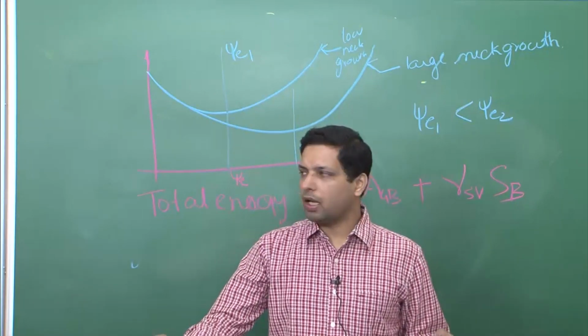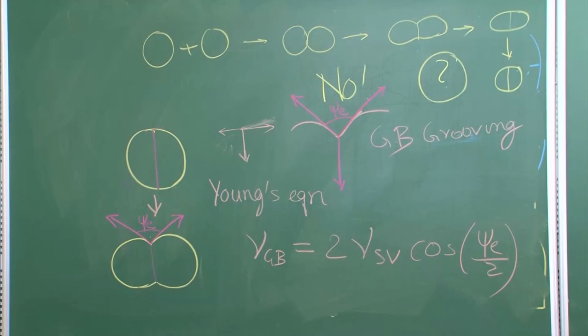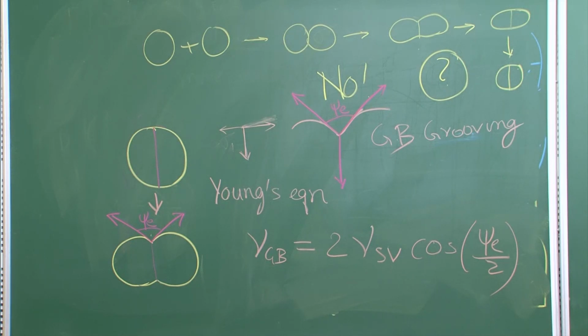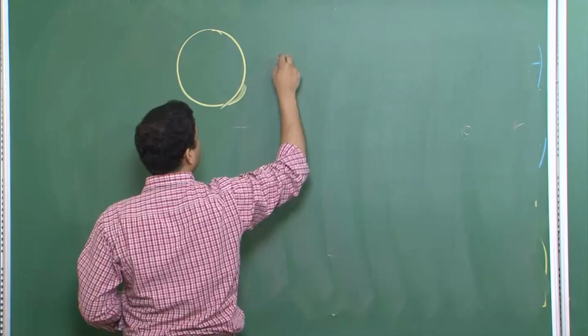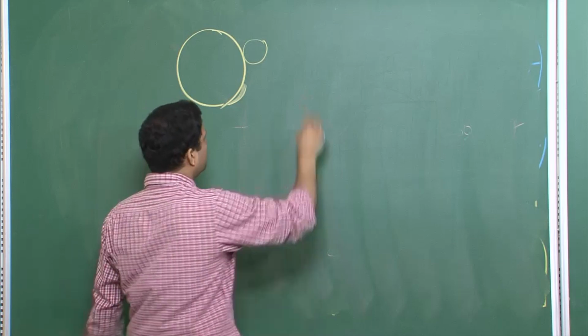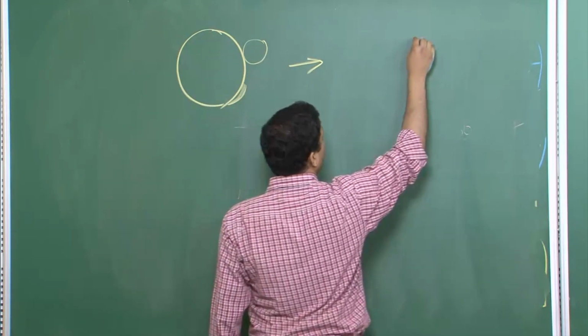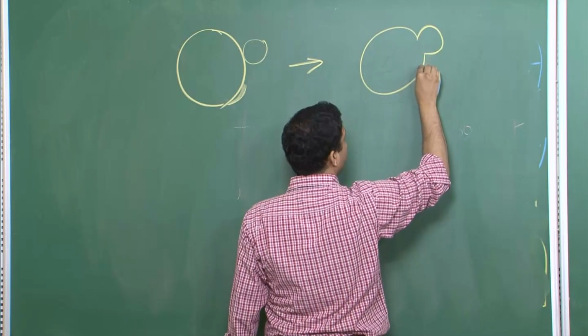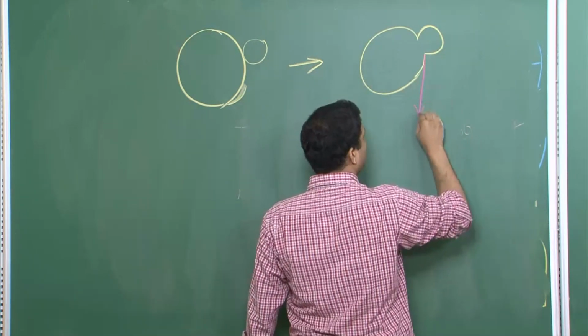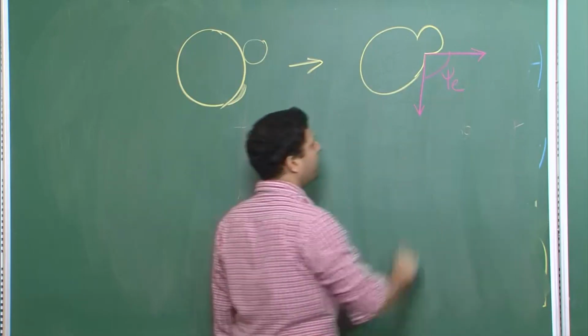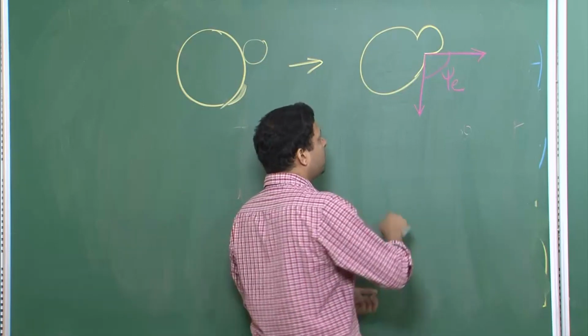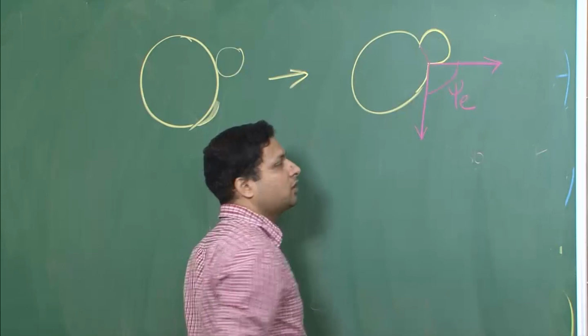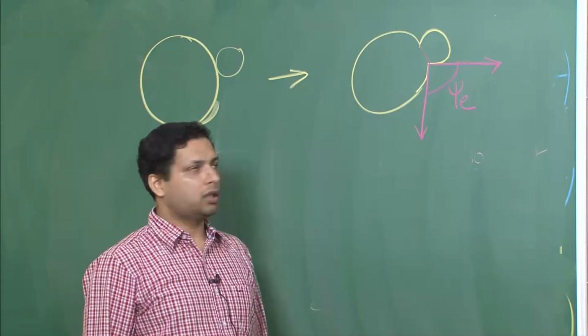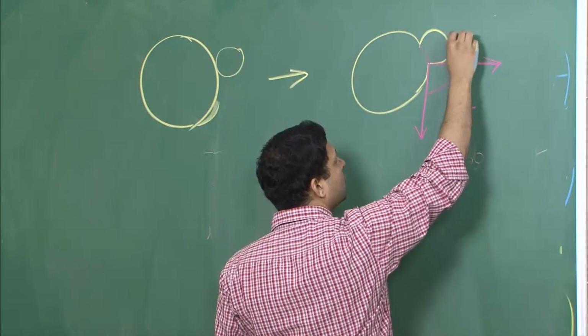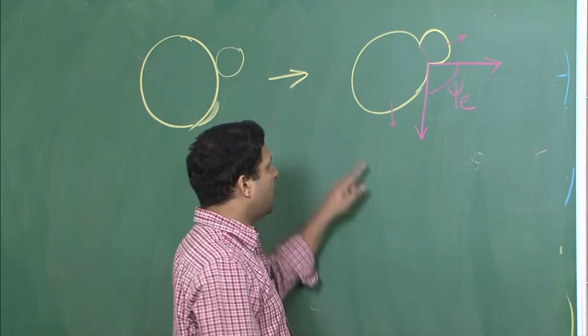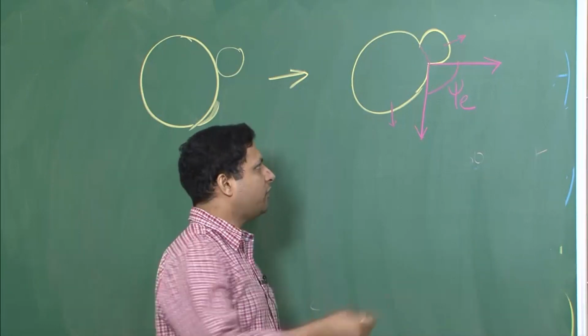Now, let us ask ourselves that here we have taken that the two particles are of same size. What if one of the particles is much smaller than the other one? So, let us say this time I have this plus a small particle. Now, if we follow the logic that we described earlier, we would get an equilibrium psi. So, this is some psi value, the equilibrium psi value. However, now note that the particle radius is smaller over here and particle radius is larger over here.